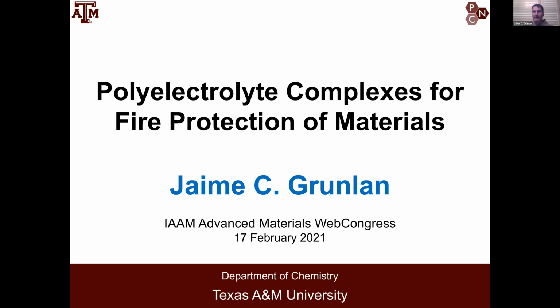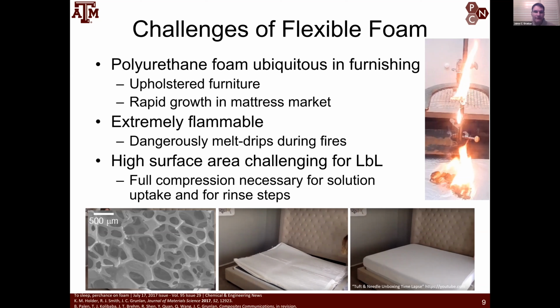On flexible polyurethane foam, it's also used in upholstered furniture, and throughout the world it's used for seating in automobiles, etc. It has a big problem with flammability and melt dripping. We've successfully flame retarded flexible polyurethane foam using layer by layer assembly, but also using polyelectrolyte complex coatings, which are much faster and easier to deposit, as I'll show later. I may not have time actually for the foams, but I'm just mentioning that we are able to flame retard. You can see this publication at the bottom highlighting that.